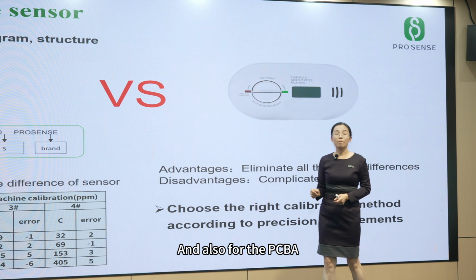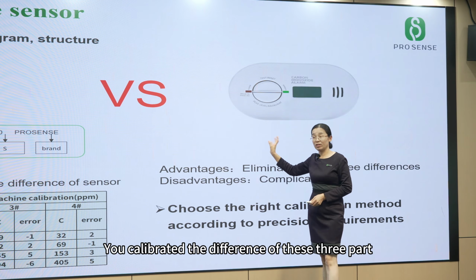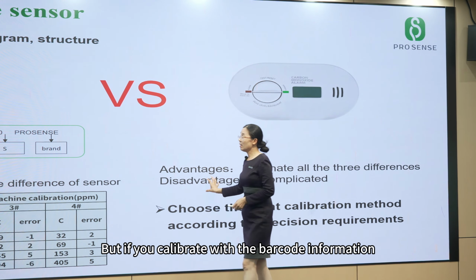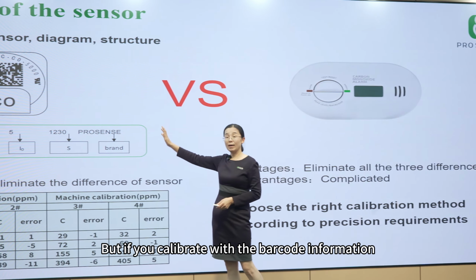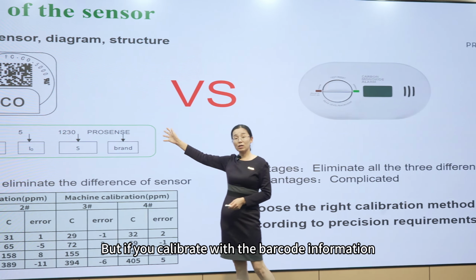It also needs compensation. So if we calibrate with the carbon monoxide gas to calibrate the detector, you calibrate the difference of these 3 parts. But if you calibrate with the barcode information, only the difference among sensors is calibrated. So please make sure that you had better use this way to calibrate the detector.